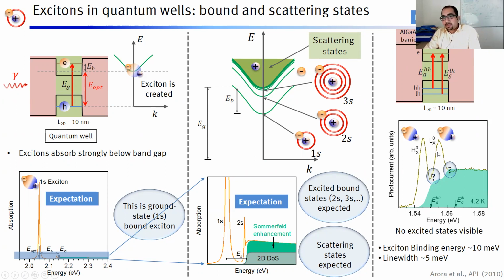And if you measure the absorption spectrum, it appears like this. So there is a heavy hole exciton, there is a light hole exciton. And then you have this step-like function. One step comes from the heavy holes and the other step comes from the light holes. Okay, so these are the scattering state contributions.